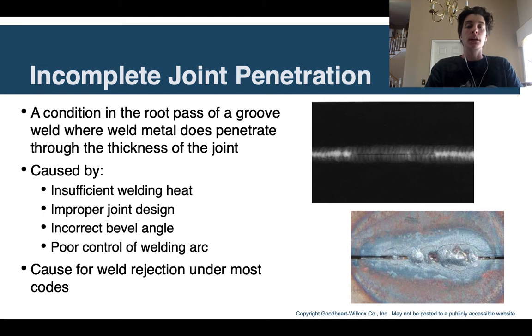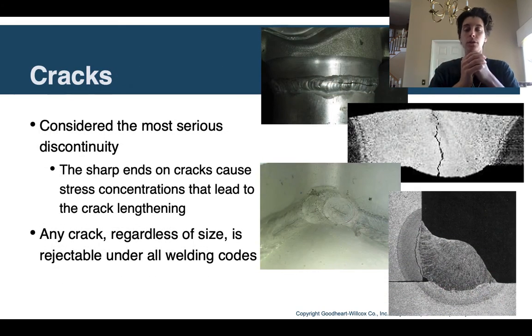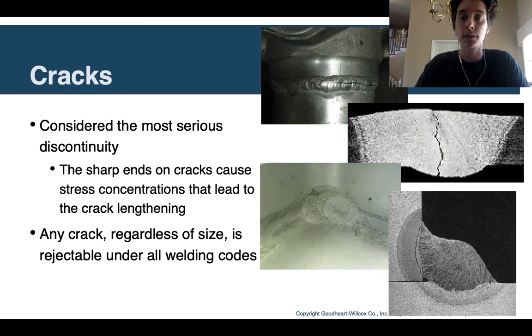Another problem is incomplete joint penetration. This would be in the root pass of a groove weld, or if it's a single pass weld, the first weld that you do, the only weld that you do, where the weld metal does not penetrate through the thickness of the joint. This again is caused by insufficient welding heat, or too low of a voltage when you're adjusting the voltage on the front of your machine. It can also be poor joint design, a bad bevel angle in your weld, and poor control of the welding arc, your actual process when you're welding. This you can see in visual inspection, and it is going to be a cause for rejection under almost any weld code, so something to be avoided.